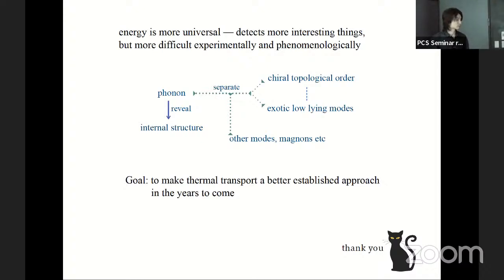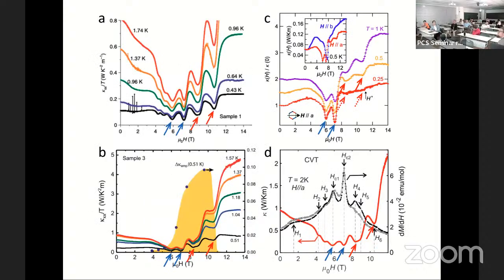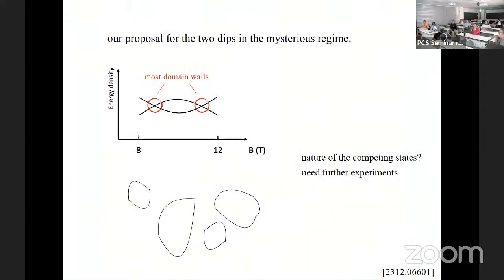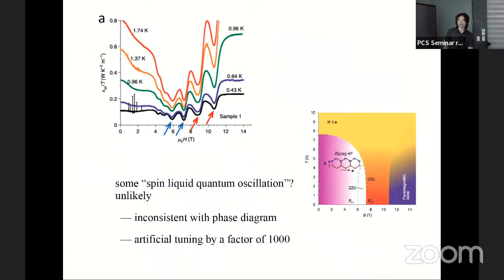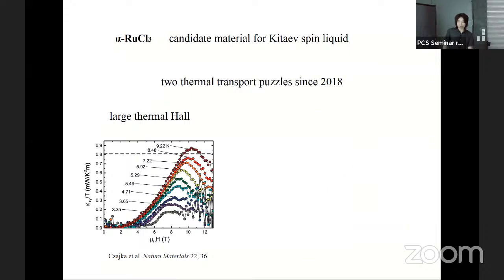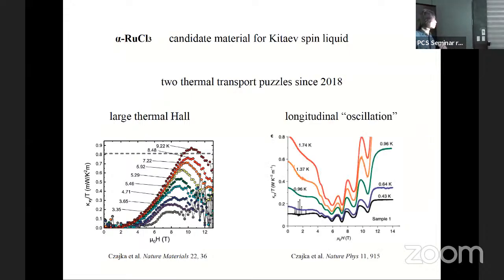In the last slide you showed this longitudinal dip in the longitudinal flow part. If you consider the magnon contribution to the thermal transport, then it does not explain, right? Right, so the magnon has a gap, right? That's a very good point. Let's emphasize this point. These two data, we think the magnon explanation is very plausible, and this we think is phonon interacting with some other things. What about magnon plus phonon?